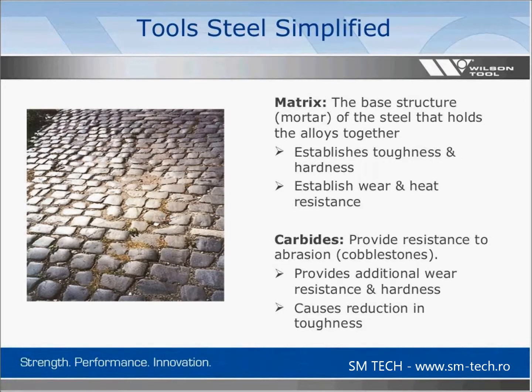The second component that couples with the matrix is the carbides. The carbides are what actually provide your wear resistance to abrasion. In the illustration to the left, your cobblestones would be your carbides. Again, carbides are hard. They provide additional wear resistance and hardness to the tool steel. However, because they are harder, they can cause a reduction in the toughness or the shock resistance of the tool steel.